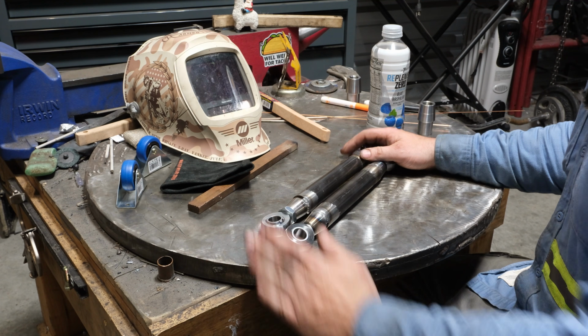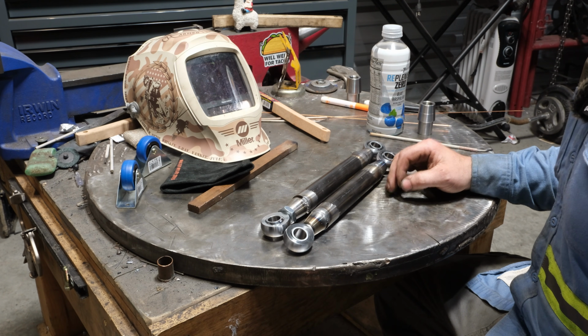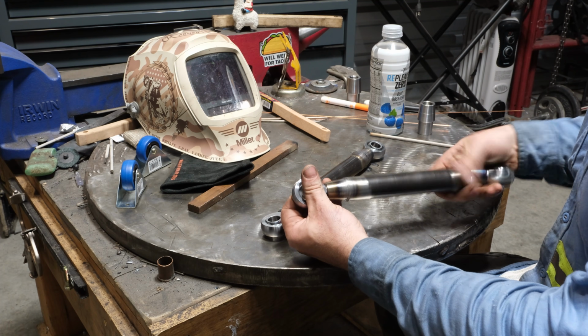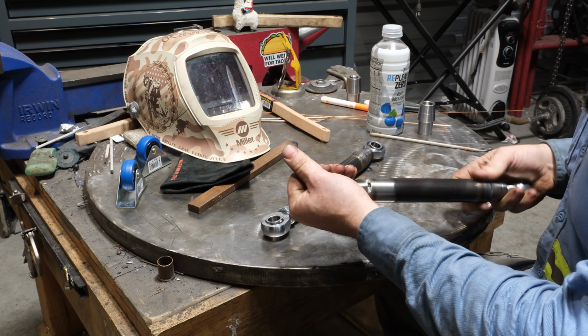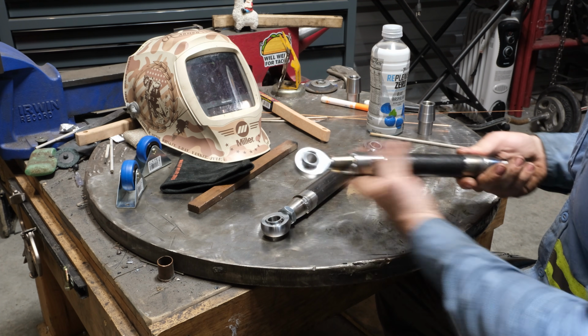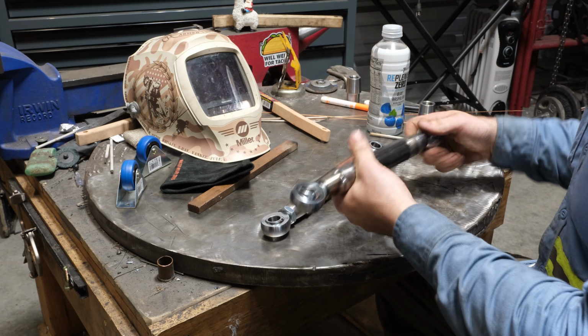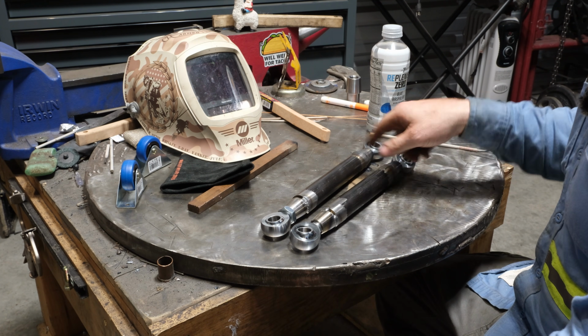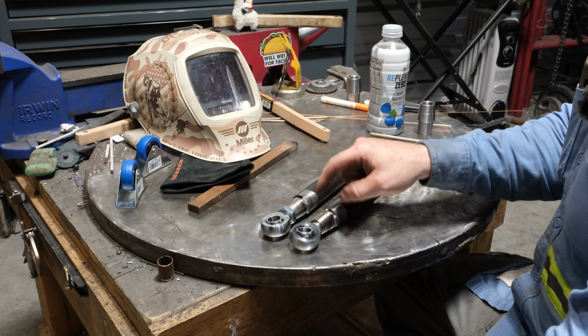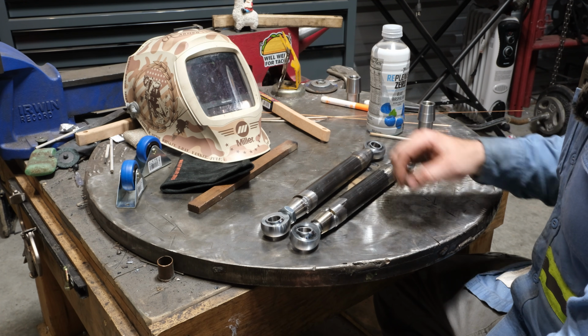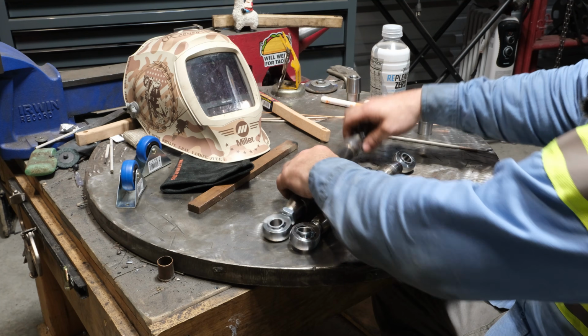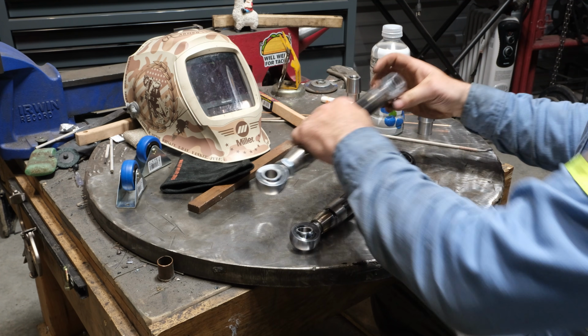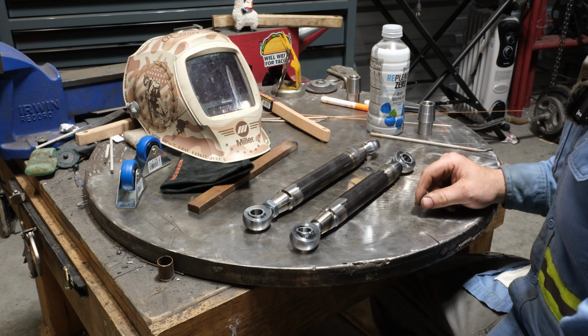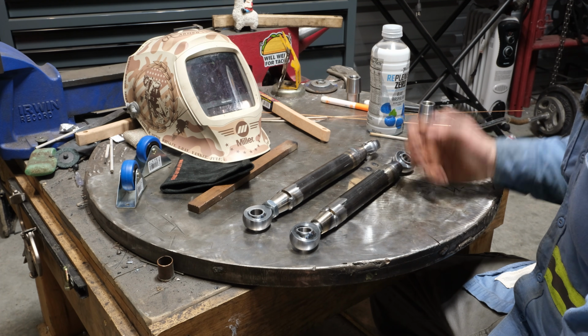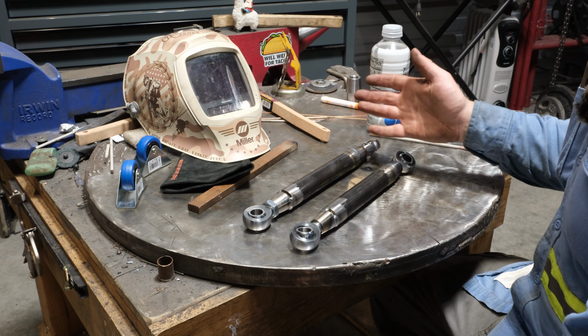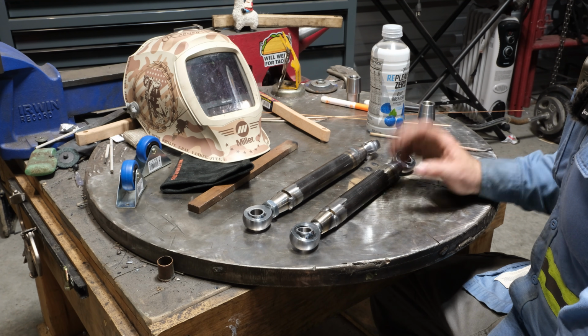Well, I got them all welded up, and we'll take an up-close look at them in a minute. I'm happy to report all of them thread in no problem, which is good, and I expected that because I left that little whisper of a gap, and that makes all the difference in the world. If I had to pick one as being the tightest, no doubt the MIG weld and the stick weld are a little bit tighter, but they thread in just fine. No real issue. The TIG is probably the loosest per se. It feels like there's nothing in the threads at all, but it really doesn't make any difference because guess what? All of these worked and we don't have to chase threads.